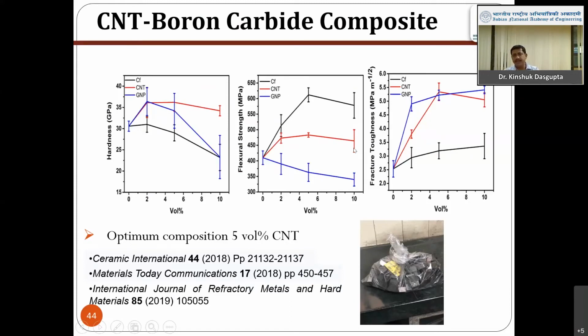So what I want to say here is that with carbon nanotube we can get improvement in all three properties, hardness, flexural strength and fracture toughness, in a reasonable value with, say, 5 volume %. And as we have the ability to make carbon nanotube on a large scale, we can add carbon nanotube to boron carbide on a large scale and make the tiles as required. Here we have shown almost 500 hot pressed tiles of carbon nanotube and boron carbide.